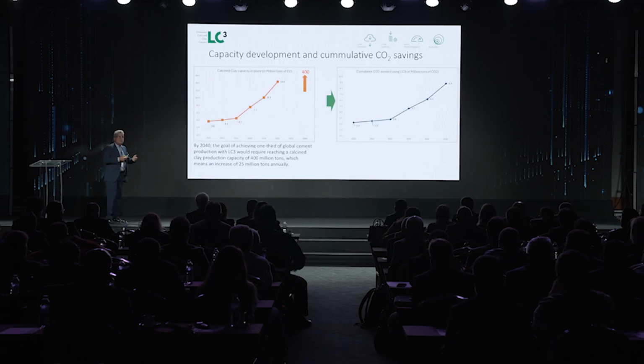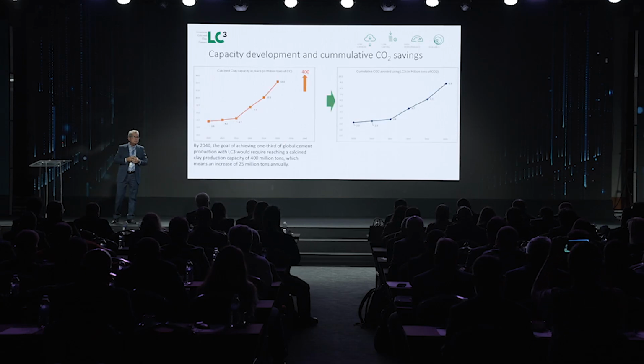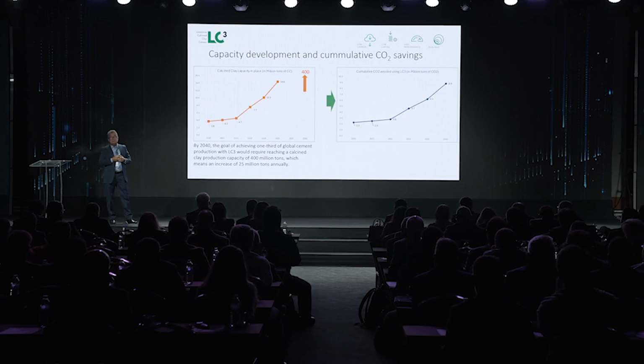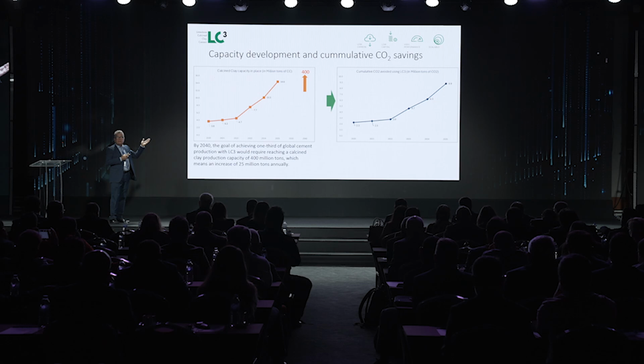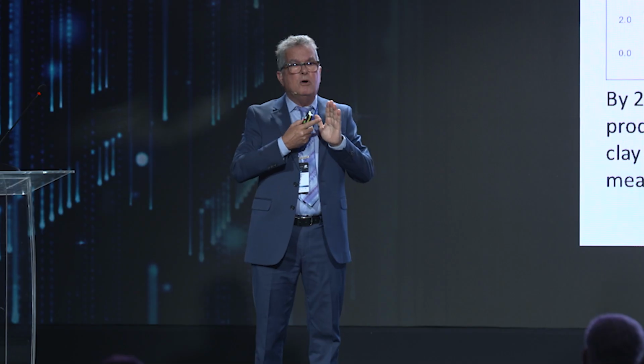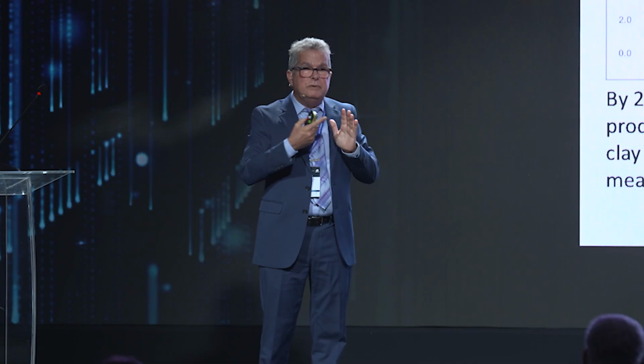And by doing this, only this year, we're forecasting that the production of calcined clay will be around 15 million tons. 15 million tons means that we're going to save around 9 million tons of CO2. But we're not happy with this, because our target is to produce up to 400 million tons of calcined clay, and by doing this, we're targeting more than 500 million tons of CO2 to be saved, and we hope that we can do this in the next 20 to 30 years, meaning this is going to be a significant impact on climate change.